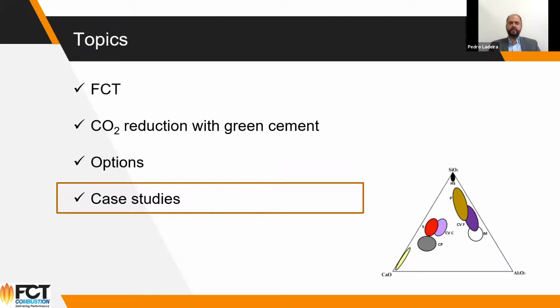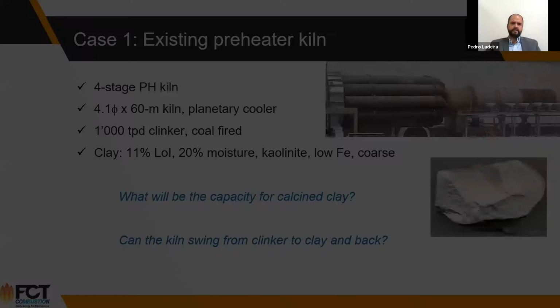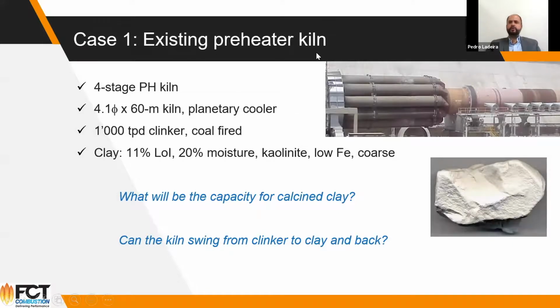So now we're going to show quickly case studies from different conversions or new plants we've been studying with our clients. Basically, we take an existing preheater kiln. Many people have kilns, they have idle kilns, and they want to convert to calcined clay. So let's pick an example here of a 4-stage preheater kiln. It's a very common size of kiln, 4.1 by 60 meters long, planetary cooler kiln, producing 1,000 tons per day of clinker. It's a coal-fired system. It's a clay with 11% LOI, 20% moisture, kaolinite kind of clay with low iron, and it comes coarse.